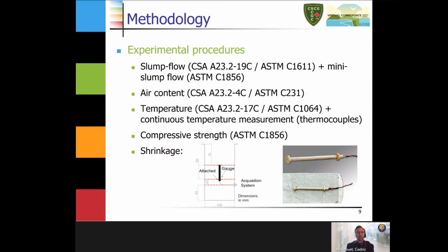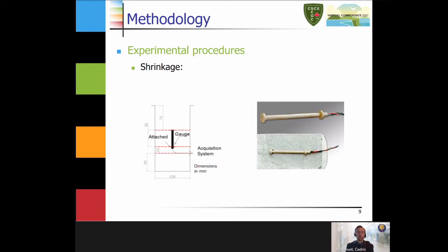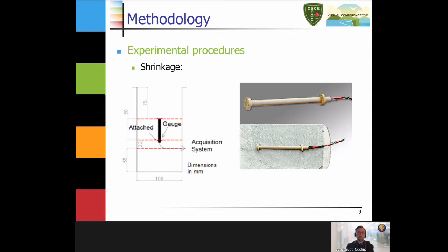We tested the slump flow of all the materials we poured in this project. We tested as well the mini slump flow, the air content, temperature of the fresh concrete. We measured the temperature with thermocouples as well. We measured the compressive strength, and we will focus in this presentation on the shrinkage of the material. So the shrinkage was measured with these kind of sensors. Basically we install the sensors in the mold, and then we pour the concrete in the mold so that the sensors are completely embedded in the concrete, and it allows us to measure the deformation of the concrete straight when the concrete is poured in the mold. So that's very interesting when we study the early age shrinkage.